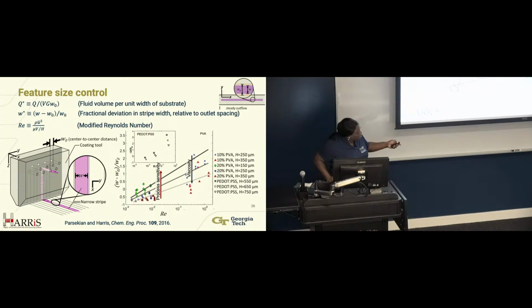And then here we have the viscosity, but with the viscosity we see larger changes, and this is the PEDOT:PSS. The scale was too different for us to put it here, and so it has its own unique set of properties, but we see that it's still sensitive. As we increase that speed, you get more dispersion. Here, you get less.